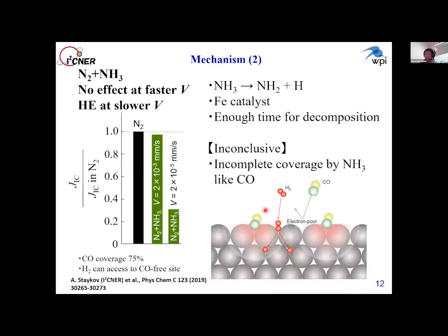Regarding the mechanism that NH3 had no effect when the loading rate is high and caused hydrogen embrittlement when the loading rate was low, we considered the decomposition of NH3 into NH2 plus hydrogen by the help of Fe catalyst. We think this decomposition may be a time-consuming process. Then the effect of this reaction didn't appear when the loading rate was high. In addition, we can think of a different story.